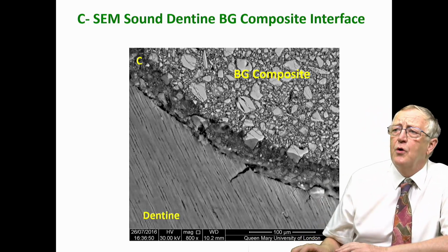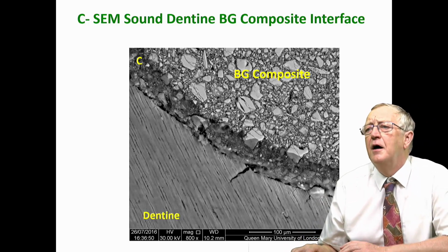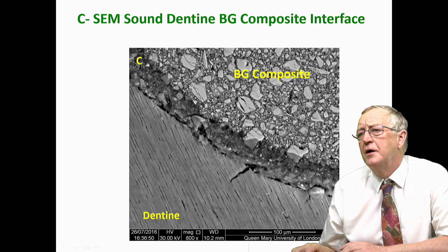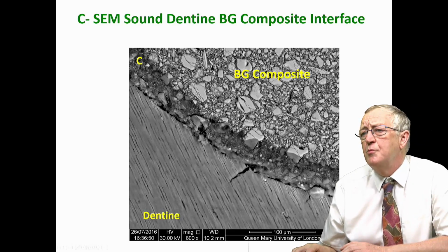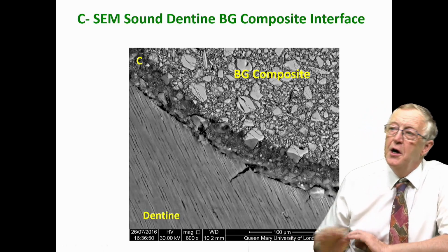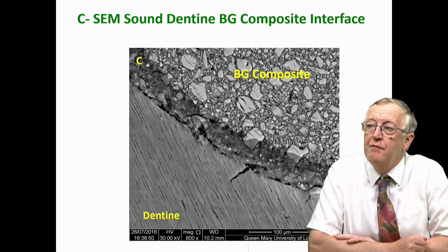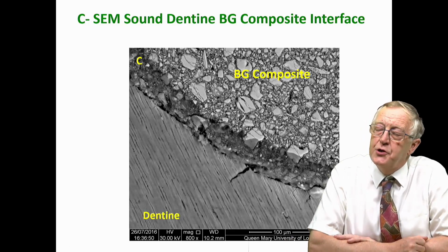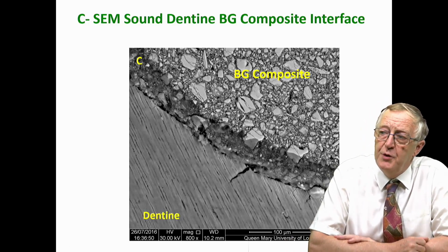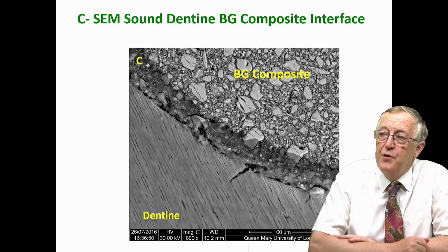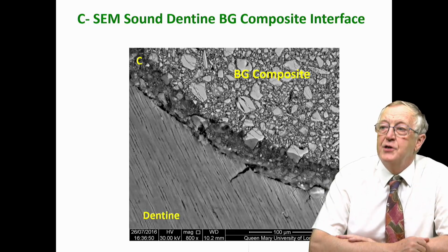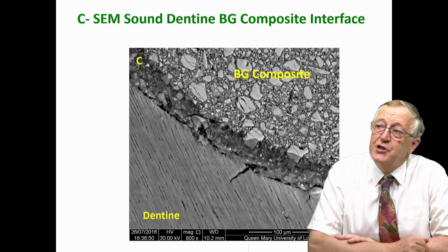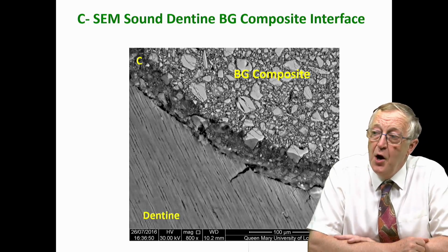But if you look carefully, have a look here. If you look carefully at the dentinal tubules, you can see a white deposit on the inside surface. And this is the apatite forming on the inside wall of the peritubular dentine like we had with the toothpaste. So this is not remineralization, this is just extra mineral forming within the dentinal tubules.